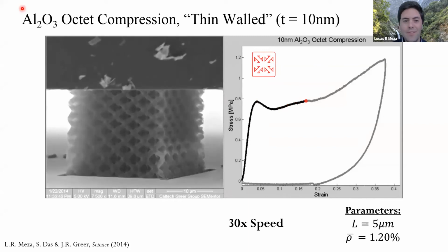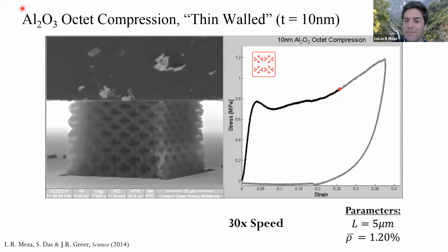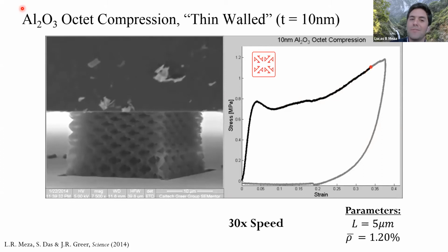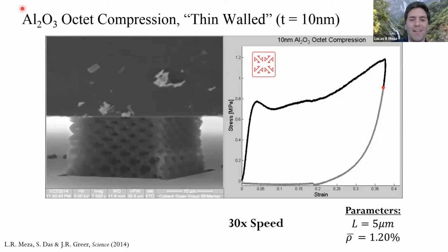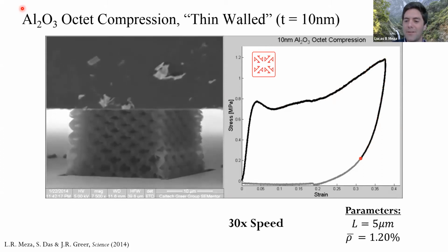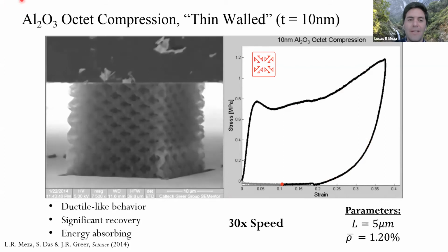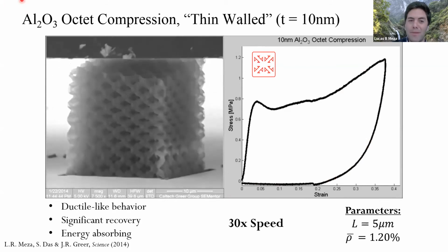Instead of that catastrophic brittle failure, you can see this gradual ductile deformation up till about 40% compression, then we unload, 40% compression, then we unload. And actually it bounces almost all the way back. Some of these structures actually recover 98, 99% of their original height, which is pretty remarkable given what we had seen for the fully dense, or thicker walled structure.